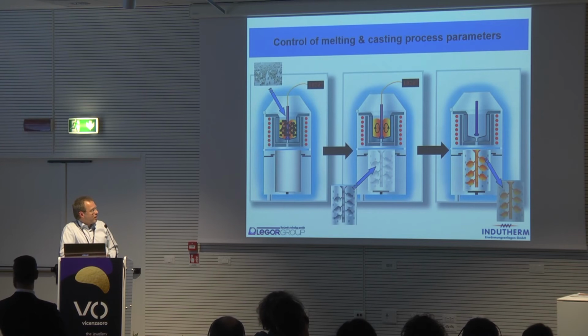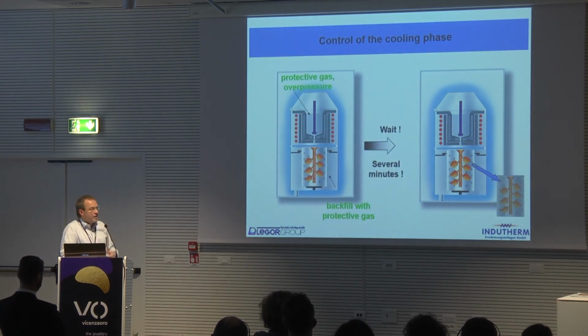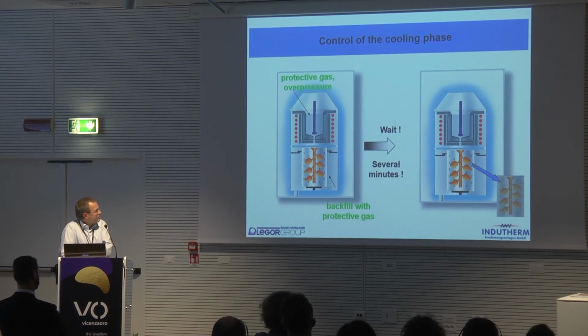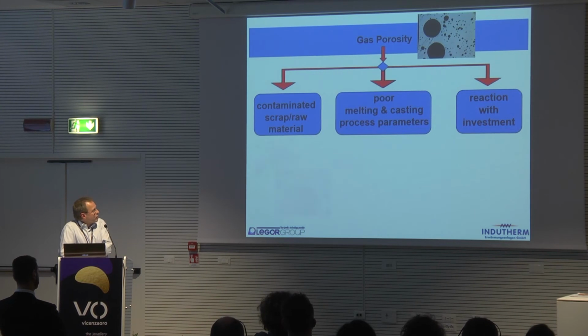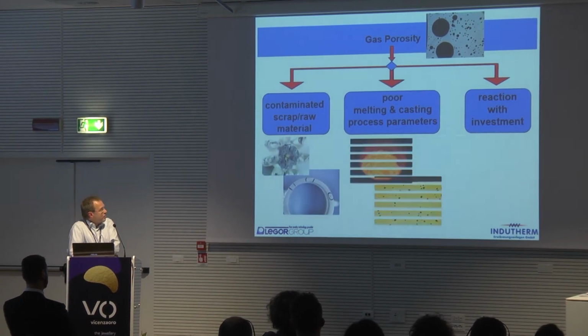Just the same, after casting, we should not take out the flask immediately from the machine in order to accelerate the process. It will greatly improve casting quality if we wait and keep the flask inside the machine for a while before taking it out, benefiting from the good atmosphere that we have in the machine. So up to several minutes can be helpful, even if it means maybe fewer flasks per hour. So we have already talked about these 2 aspects.